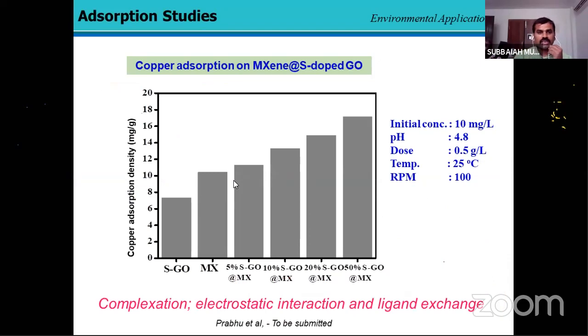I have also started some work on copper adsorption. We have started some copper adsorption studies with the help of MXene materials, which showed higher adsorption capacity. Initially we started with the sulfur-doped graphene material for copper adsorption, since sulfur is a soft moiety which can easily adsorb copper, as we know from the well-known HSAB principle.